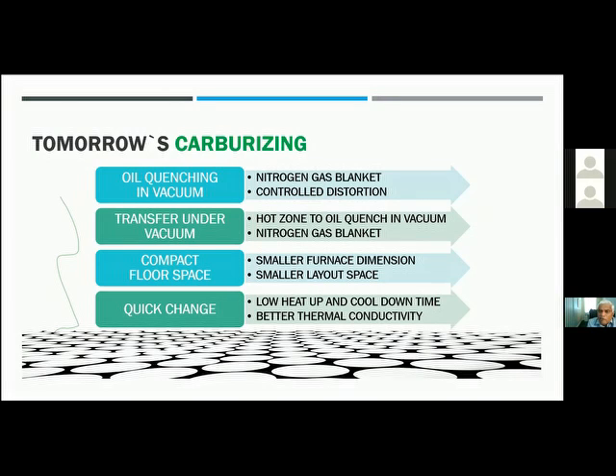When you talk of quenching, whether it's helium or nitrogen or argon or oil quenching in vacuum, there is always going to be distortion. And one of the panaceas that people expect, and that bad marketing people try to market for low pressure vacuum carburizing, is to say there is no distortion when you use vacuum carburizing. I would like to personally advise you, any steel, anytime you take any steel machine product to high temperatures, austenitizing temperatures, and then quench it by natural thermal forces, there is going to be distortion.